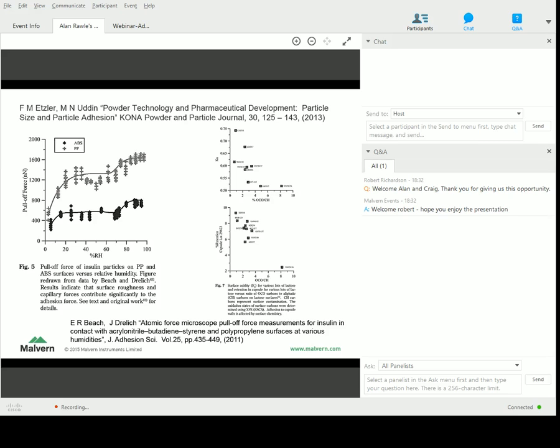A practical illustration of this is a paper by Etzler and Uddin in Kona, which is a Hosokawa publication from Japan, and I just illustrate that to show real-world particles and some of the issues that are faced when we try and make a pharmaceutical. This is insulin. This shows the various differences that occur with varying levels of humidity and greater attraction as you increase the humidity. So we take our material, we might make it in a dry winter, we ship it out to, say, Singapore or Hawaii with a big humidity, and we find that particles are stuck together very nicely, and that drying between surfaces, if they're reprocessed afterwards, can cause significant issues. We're not going to separate the particles out again by drying them.